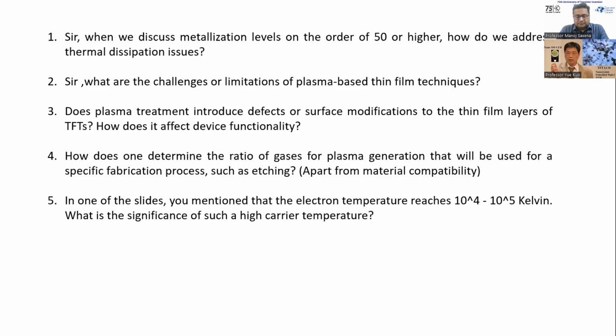For example, for the amorphous silicon TFT, with plasma radiation damage, when you etch the film, you damage the layer on the surface, where we show the surface composition change and the bulk film ESR signal changes. Because the film deposited by plasma at low temperature is full of defects, the dangling bonds are passivated, but only weakly passivated. So radiation can damage it.